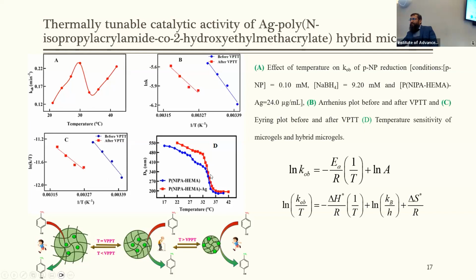The volume phase transition temperature of the hybrid microgel system was also evaluated to confirm that this decrease in rate constant is actually associated with the volume phase transition temperature. The value of the volume phase transition temperature was evaluated using dynamic light scattering, and this value perfectly matches the lowest value of the rate constant at a particular temperature.